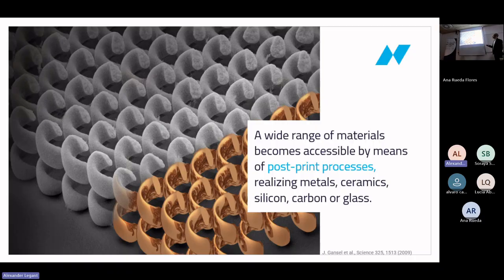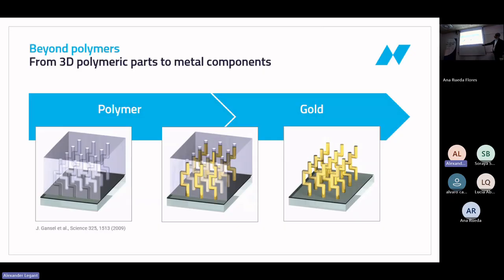And not to forget, here we see some gold examples by electroplating. What you typically do is start with a positive tone resist. That means you start here with this block. You expose these helical structures on a conductive layer. Afterwards, you put the sample into an electroplating bath, and the gold structures then grow, and of course you stop at a certain point. And after burning away the outer polymer, you have the freestanding gold helical structures.